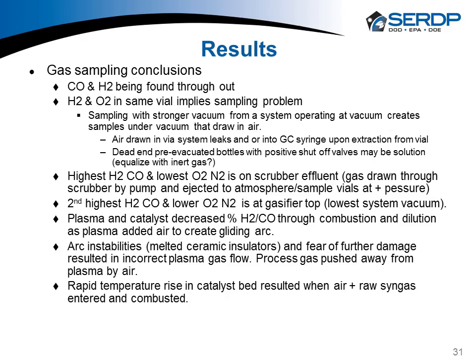From the gas sampling conclusions, we did see CO and H2 throughout. Again, not enough statistics to really get good numbers, but some interesting things. We see hydrogen and oxygen in the same vial, which does imply a sampling problem. And when thinking about it in retrospect, we're sampling with a stronger vacuum from a system that's already operating at a vacuum.